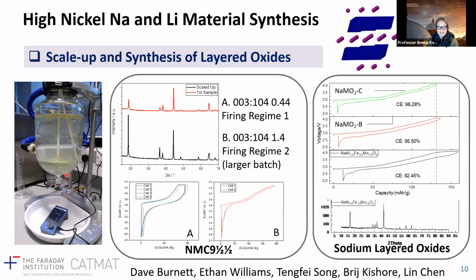Using this methodology, you then filter and dry and then mill this material with the lithium hydroxide, and then you fire it. And by controlling your firing conditions, you can either make a pretty rubbish material or quite a good material. And although it's made in exactly the same way, it's got the same precursors in, the firing is extremely important to maintain the cation stoichiometry and limit any nickel lithium mixing within the system. And typically you can tell this from the XRD patterns by the ratio of this 003 to the 104 peaks that you see here.